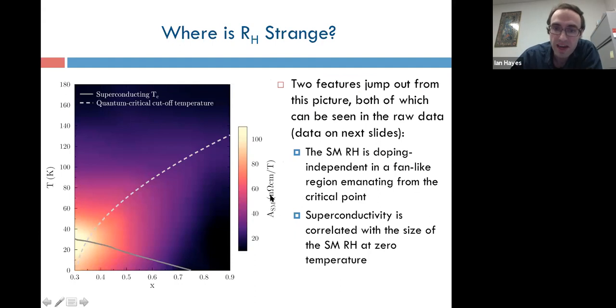So when you do that, this is what you get. This is an intensity plot for that strange metal field dependence in the doping and temperature plane. And I've started here at 30%. I've neglected the underdoped part because the transition to the antiferromagnetic phase involves reconstruction, as we heard in the last talk. And that radically changes the Hall coefficient and gives you different field dependence. So to compare apples to apples, we're going to stay on the overdoped side. And there are two things I really want to draw your attention to about this phase diagram. The first is that if you look at high temperatures, the strange metal part of the Hall effect is independent of doping. Throughout the very broad region of doping space, you simply get the same field dependence for all your samples. As you decrease the temperature, the window over which that is true decreases. And it decreases continuously and seems to vanish near 30%.